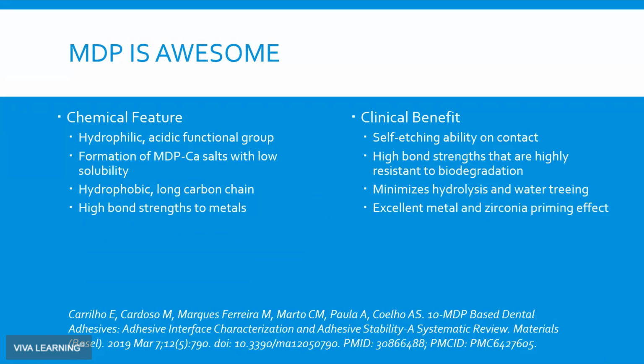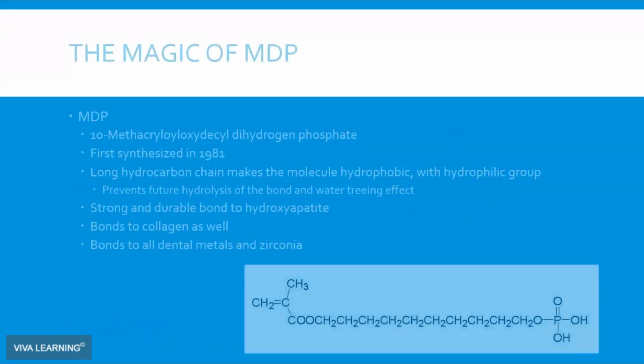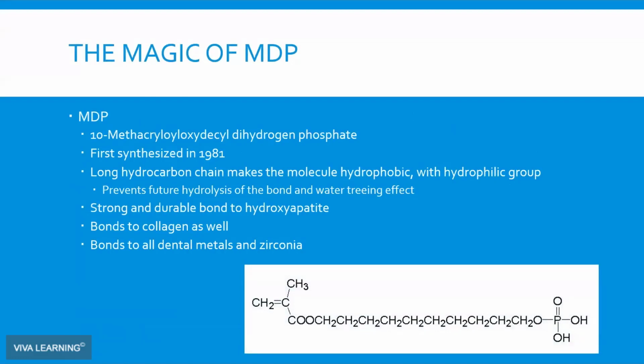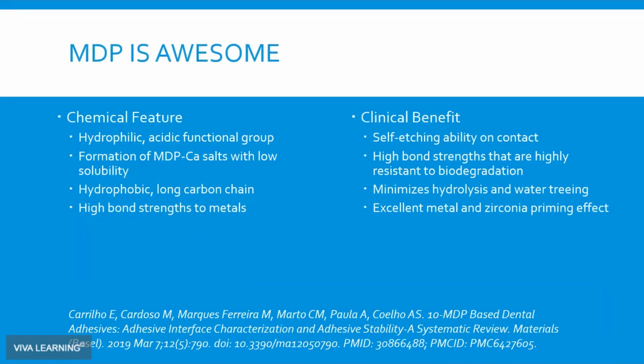So MDP has several chemical features that have a direct clinical benefit. The first I didn't mention, but on one end of that molecule you have this hydrophilic acidic functional group, a phosphate type, which you'll see here on the lower right of that screen, the phosphate group there. And what that does is it starts out at a low pH, which gives you self-etching ability on contact. Now, the dwell time is important. Some people argue not just the dwell time, but also mechanically scrubbing it in. I can't comment on that other than to say that with and without, I've had excellent results.